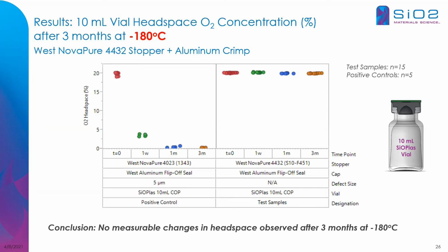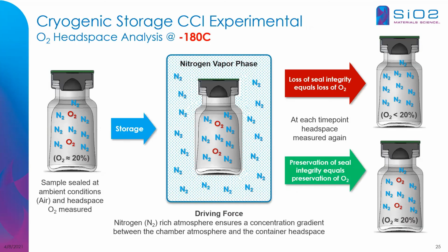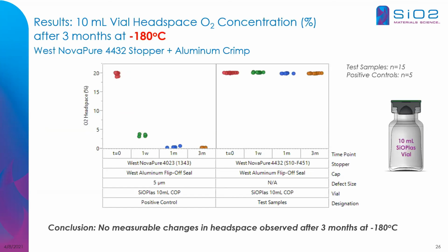So what's happening is the nitrogen, the gas surrounding the container in the chamber, is migrating into the container. And so you're getting a decrease in oxygen because you're getting an increase in nitrogen. In the case of the test sample, over 3 months, the oxygen level is holding at 20%, which is the initial oxygen that was in the container at the start of the test. This test will continue for up to 1 year. So what we have here is a very robust container that doesn't break and also can maintain container closure integrity up to -180 degrees C.